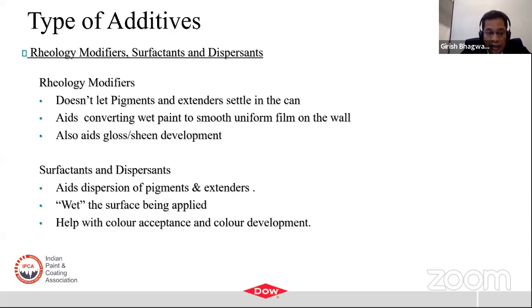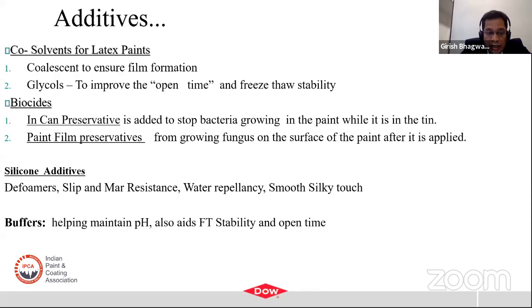We also add additives like co-solvents that are added in paints for improving the open time, making sure the coalescence takes place, because the suspended polymer particles eventually have to merge. Otherwise it won't have the resistance properties, the mechanical properties that we want to achieve. So obviously the coalescent role is very important. We also add biocides, paint film preservatives, in-can preservatives. We add defoamers, slip and mar resistance, water repellency, and also sometimes some additives to make sure that the film is smooth and silky to touch. Since it's water-based, we want to maintain the pH by using amines rather than ammonia, because people don't like the smell these days. We also add these to, to some extent, influence the freeze-thaw stability and open time.